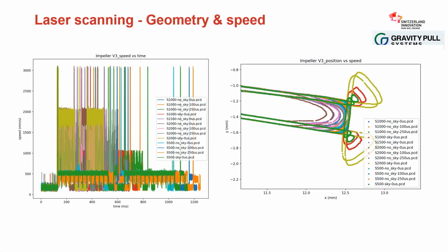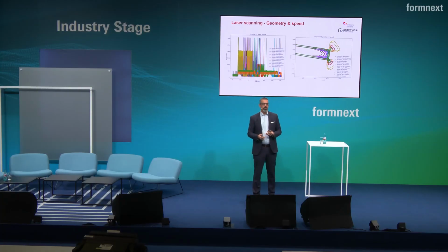For turning, so that's now we are at the tip of the blade. We see the contour run, and I don't explain everything, but you see there are some runs that are taking a short curve. That is, if the dynamics of the scanner is not sufficient to fully scan to the edge. So you end up with a geometry error. On the other hand, you see these loops. This is a so-called skywriting.